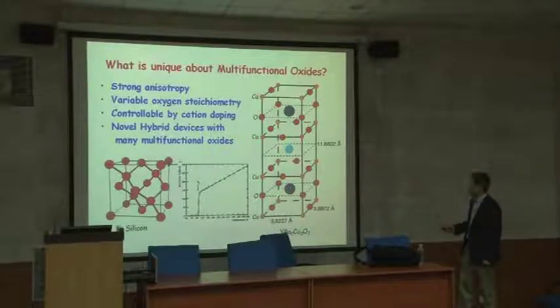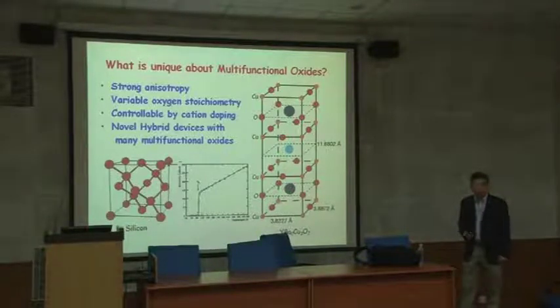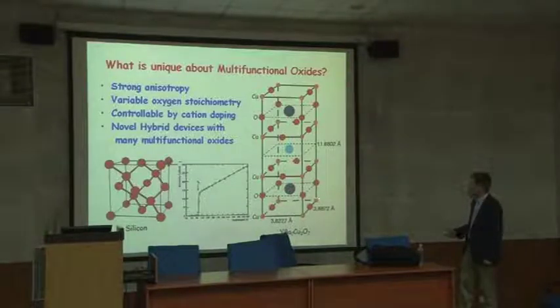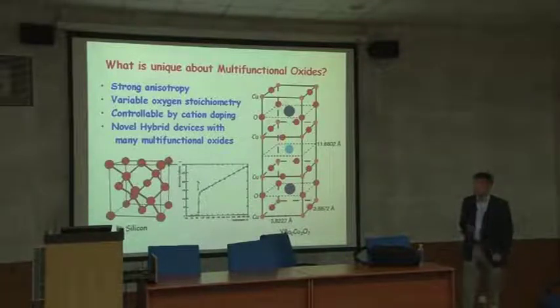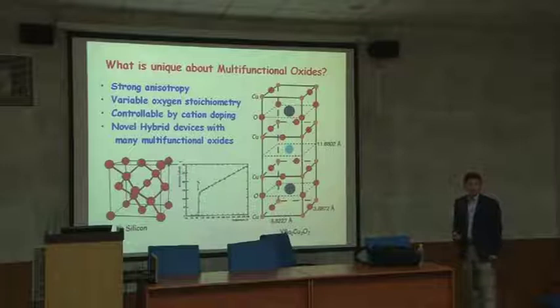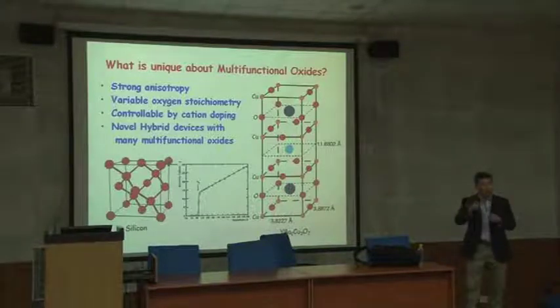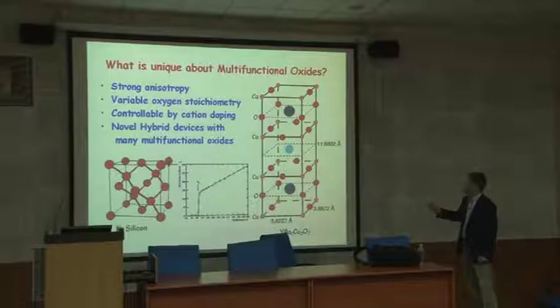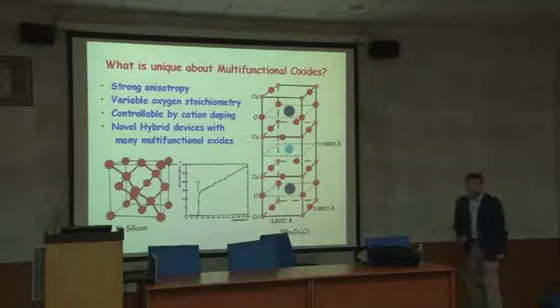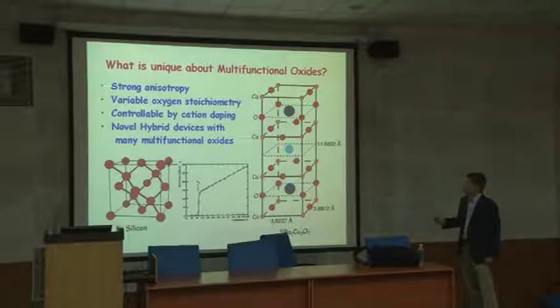But you have an A site and B site, and also your copper oxygen planes, and another important perspective in this is that oxygen goes in and out of this system, making yttrium barium copper oxide 7 minus delta, and that makes the material go from superconducting to insulating. As you can see, from the structural point of view, it is not only very complex, but this structure is very anisotropic. The coherence length, the superconducting coherence length, which means how far the superconductivity actually reaches, is much shorter along the C direction than along the A and B directions. That's what we call the very strong anisotropy.